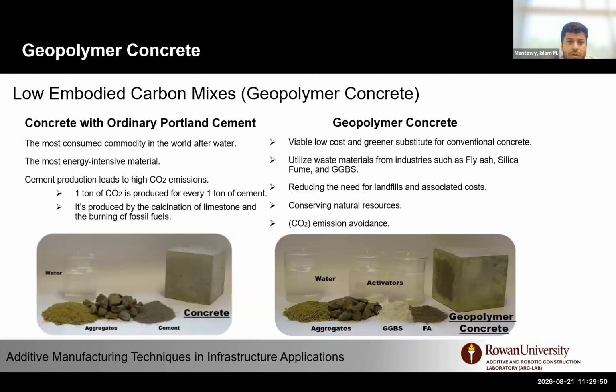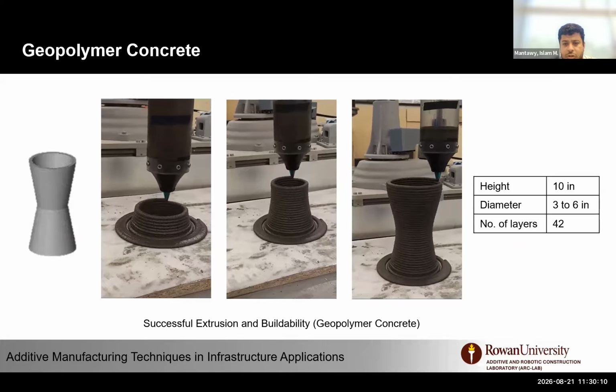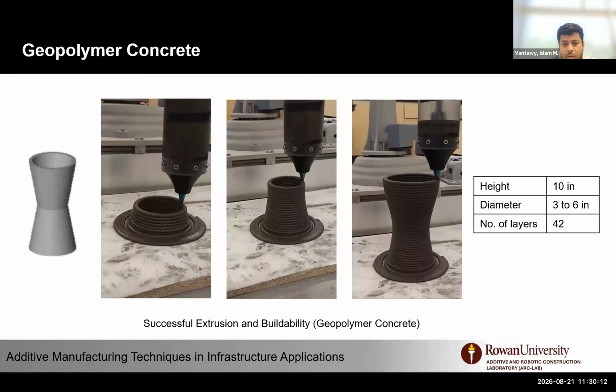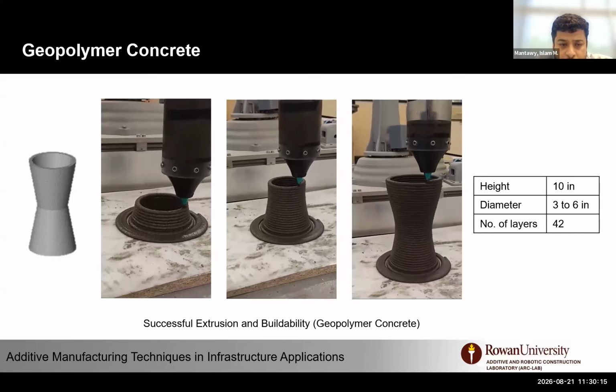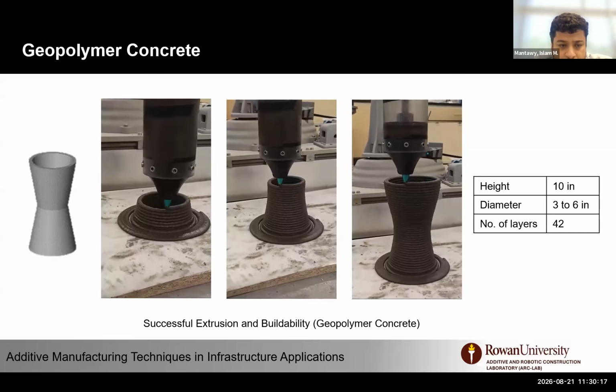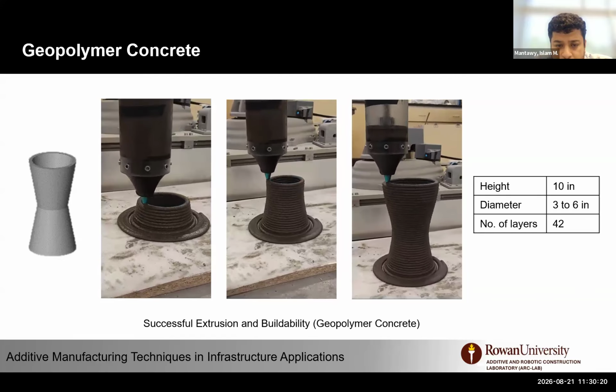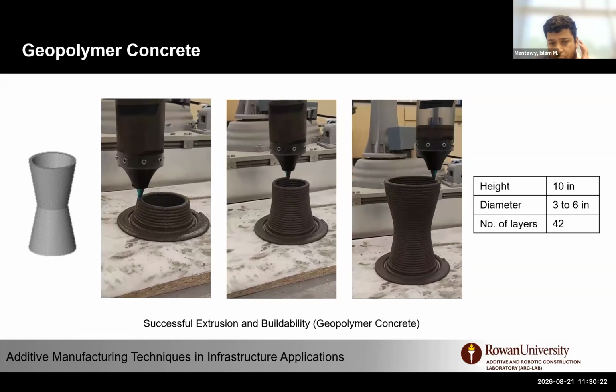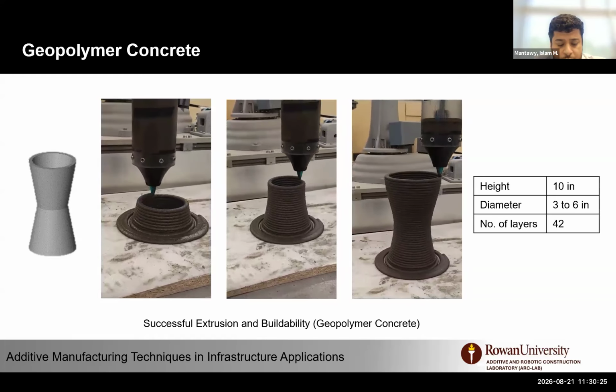We also work on geopolymer concrete. I'm pretty sure you're familiar with geopolymer concrete, which replaces cement with byproducts from different industries like fly ash, silica fume, slag, and uses chemical activators to create the binder. So we also work in that area, and it's a very challenging material. It's very flowable, but it has transient change in rheology. So we rely on those changes to start printing, and we're able to print different types. And later on, I will show you in project 3, we use that for 3D printing underwater.